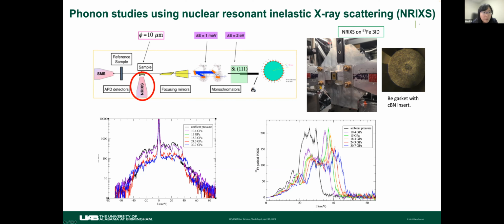Okay, so this data is taken at room temperature, and we increase the pressure and repeat the scans several times at each pressure. And this is the NRIXS data we get, and we can derive the density of states. In this case, it's done at sector 3-ID on iron-57. So here, this is the derived phonon density of states specific to the iron element. And we observed a continuous hardening of the phonon modes. For detailed analysis of the evolution of each of the phonon modes, we need to look at the data more carefully.